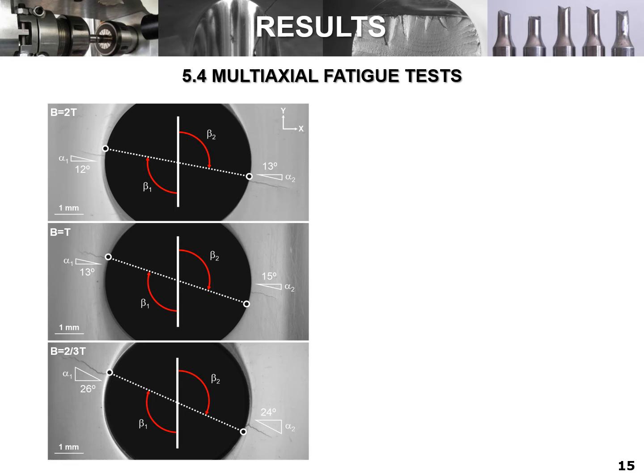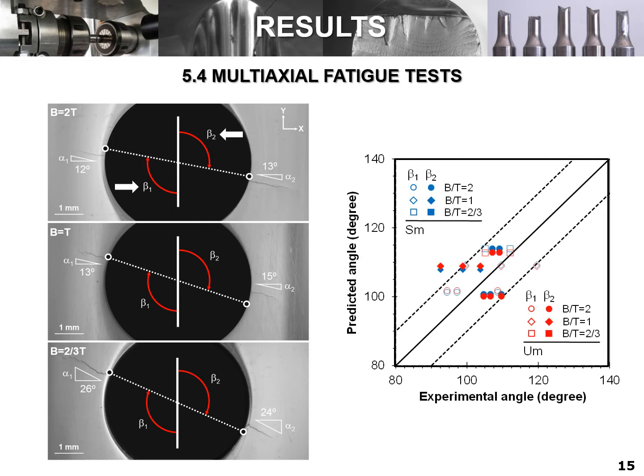The experiments show that the lower the BT ratio, the higher the beta angles. This can be explained by the greater shear stress levels associated with the decreasing BT ratios. Numerical simulations confirm these trends.